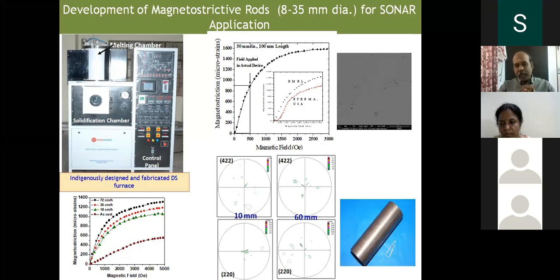In the modified Bridgman furnace, we make a seed crystal, and the seed crystal is kept over a water-cooled steel plate. The other part of the rod, which has to be melted, is kept in a hot zone. Since the seed crystal is over a water-cooled chill plate, it doesn't melt, and the other portion of the rod is getting melted. From the hot zone, I slowly pull towards the solidification chamber at a predetermined rate. The same kind of velocities have been utilized here also.